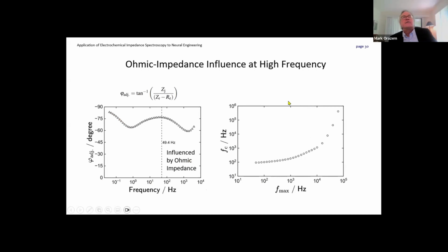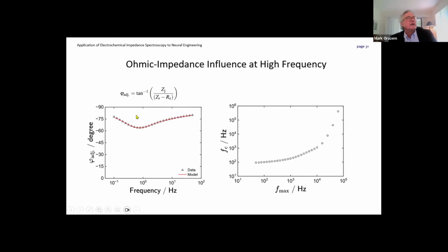Anyway, so for each of the measurements, we found a different characteristic frequency, and we used that for that particular measurement to delete points. And this is showing you what the phase angle looks like after we deleted those points.